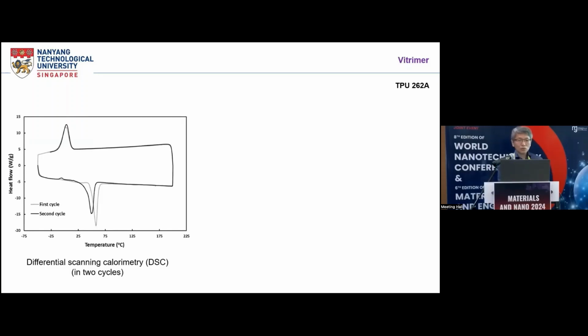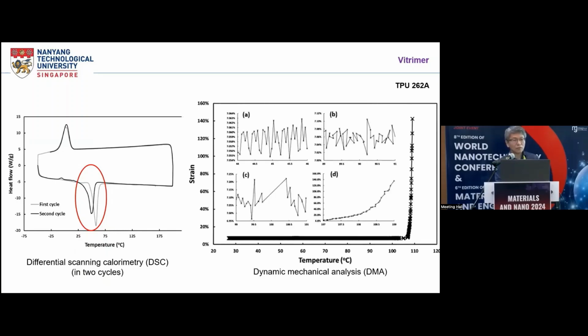This term was actually from the manufacturer. This is the brand name 262A. And if you do carry out a differential scanning calorimetry test in 2 cycles, you will find the heat flow against the temperature relationship. Over here, this trough indicates melting. And therefore, we expect that the material becomes fully melted at about 75 degrees.